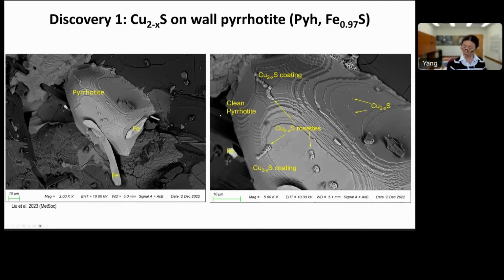This is another example. This is my favorite example because here is a large pyrrhotite grain. And when we zoom in on this area, we see that this grain is coated by copper sulfide. So you see the fine grain coating. At the edge of the coating, we see copper sulfide rosettes. They are resembling, in terms of texture, a desert rose, but much smaller, a few microns across. We also see discrete copper sulfide grains that form this kind of linear pattern on the surface, on top of the coating.